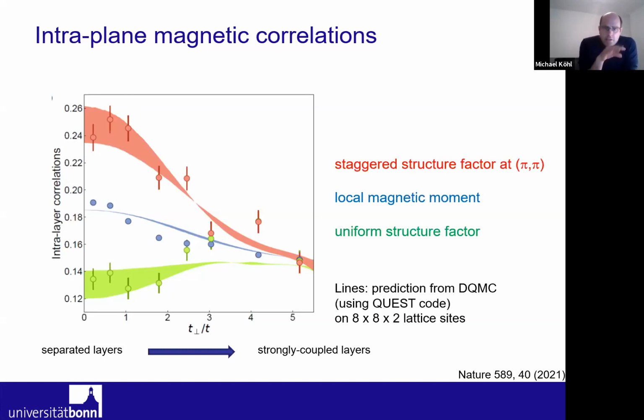And the uniform structure factor and the staggered structure factor, they should be symmetrically around this local moment, as you see here. And we basically see that for low coupling between the bilayer structure, we have a large excess at the staggered structure factor as compared to the local moment. And as we go to increased coupling between the planes, this goes away, and essentially all the magnetic information goes away. Everything collapses onto the local magnetic moment. And this is basically the situation where we lose the magnetic correlations in the system completely. So by tuning this interlayer coupling from 0 to 5 in units of the intraplane coupling, we can tune from nicely antiferromagnetically correlated states to non-magnetically ordered states in each of the planes.